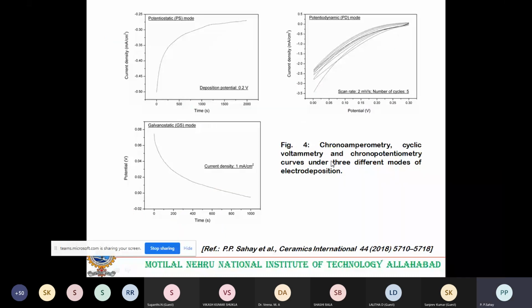This is your deposition curve. This is the potentiostatic deposition mode. Here, with reference to the AgCl, we applied 0.2 volt, that is the deposition potential, and measured the current density versus time graph. You see that the minus sign is here. So in the beginning, there is a movement of MnO4 species towards the positive working electrode.